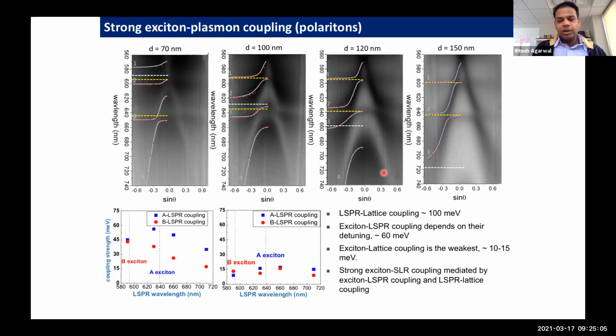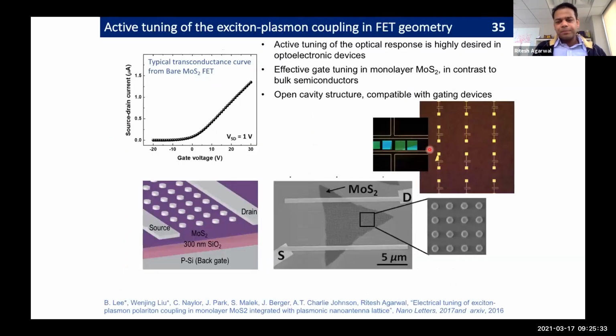So we showed inhomogeneous broadening can be reduced, and once we improved all these things, we were clearly able to show that one can create exciton plasmon polaritons. By tuning the geometry, either the diameter of these individual particles or the lattice constants, one can tune the surface plasmon lattice resonances, or detune them with respect to excitonic resonances, and create these polaritons.